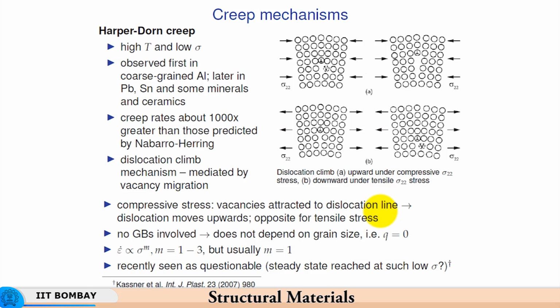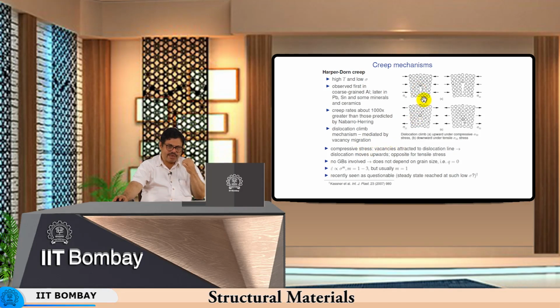Here no grain boundaries are involved, and so it is independent of grain size. Naturally, since it involves dislocations, if your dislocations are getting attracted towards the vacancies and climb is aided by the vacancy migration, then the strain rate would go up, and the sensitivity is between 1 to 3, but usually the strain rate is directly proportional to the stress applied, because you have dislocation climb which is aided by migration of the vacancies. So, basically it is a dislocation mechanism that is operational, dislocation climb being aided by the compressive state of stress and the vacancies getting attracted to the dislocation.